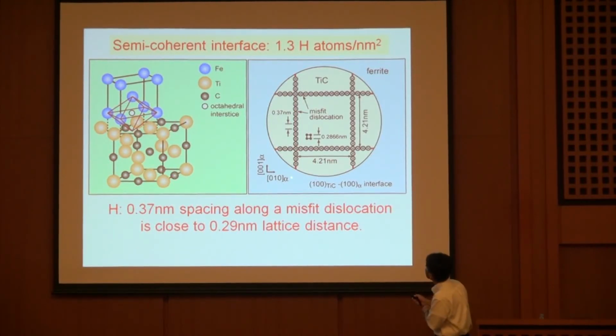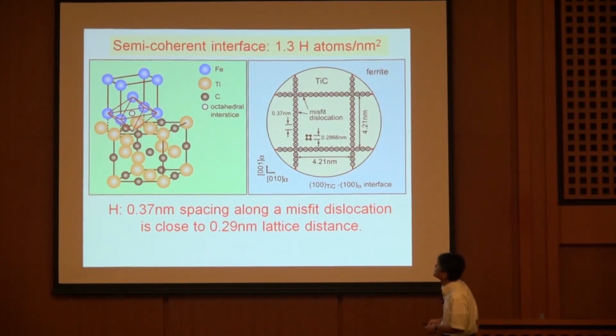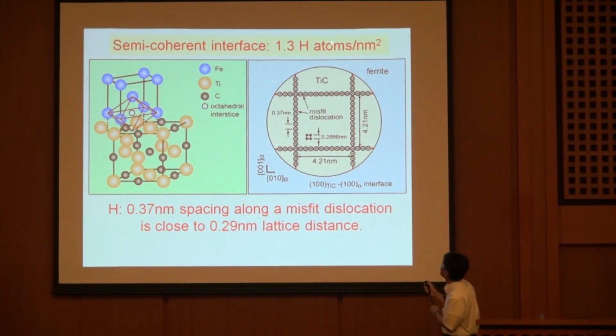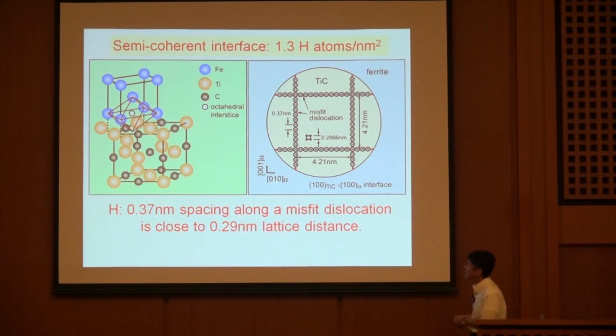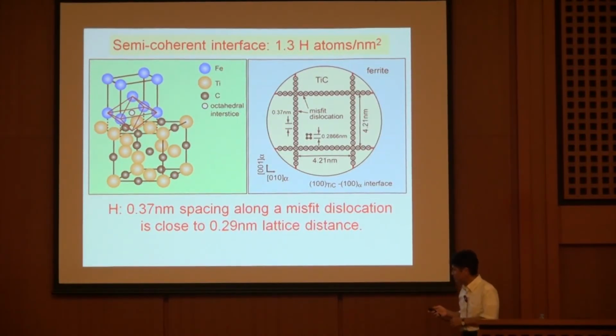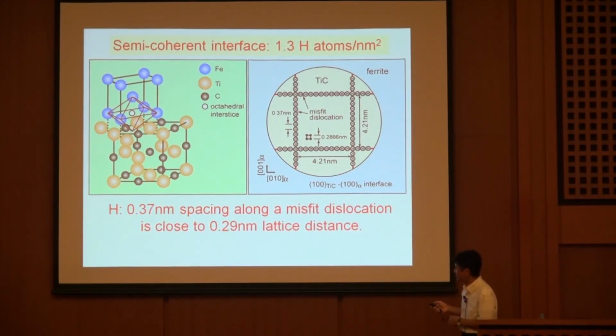So this is a picture of the interface viewed from the top. And this is the array of misfit dislocations. And what we found is 0.37 nanometer spacing along a misfit dislocation for 1.3 hydrogen atoms per square nanometer. And this spacing is very close to a lattice distance along a misfit dislocation. So this is a lucky, good coincidence between the two. So then we believed it must be a hydrogen trapping site.